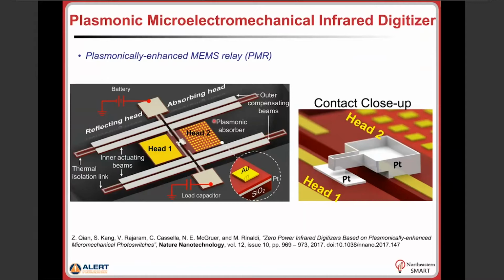Now on the head of the cantilever that carries the contact tip, we pattern this plasmonic metamaterial absorber. Again, I'm going to talk a little bit more about that later, but substantially it's a metal-insulator-metal structure, right, in which the top metal surface is patterned using these plasmonic nanostructures, these sort of patches that you see here, that are in the range of hundreds of nanometers up to a micron in side dimensions. And basically by changing the lateral dimensions of these patches on the top metal of this structure, we can select the wavelength of infrared radiation that gets very efficiently absorbed in this deeply sub-wavelength dielectric. So here we're talking about only a few hundred nanometers of dielectric, and we can achieve absorption in the mid-infrared range or so. So that's what is on the cantilever head that carries the contact tip.